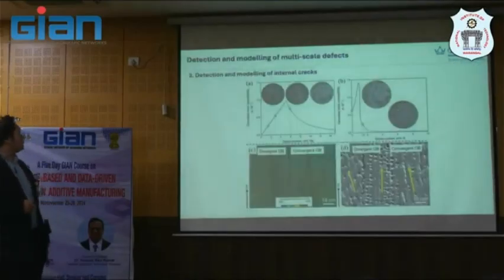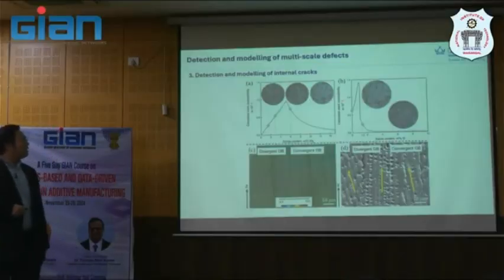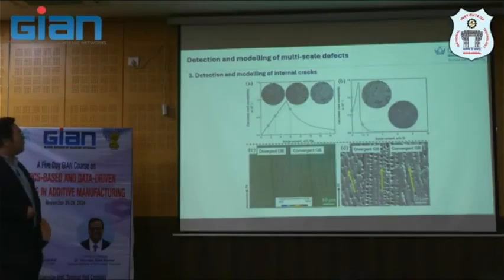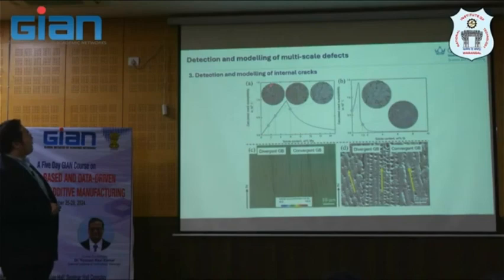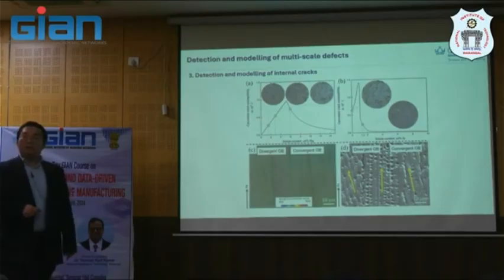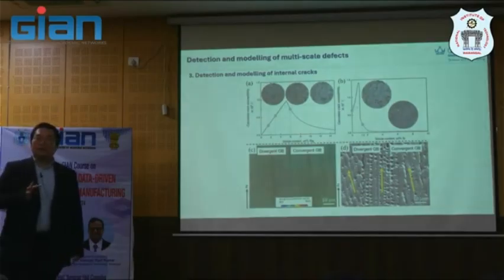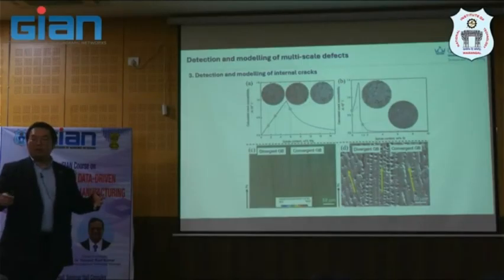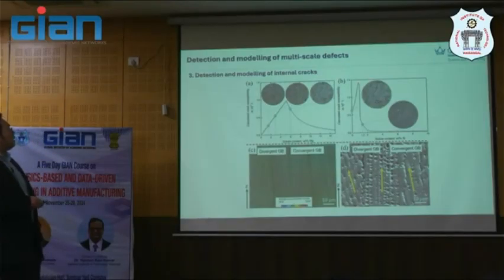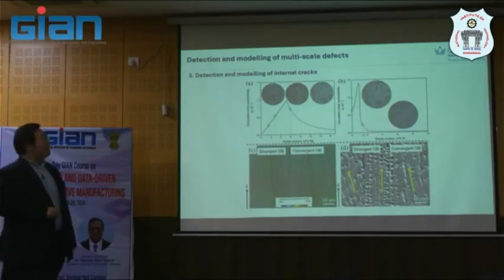printing. Next one is about internal cracks, and again this is related more to the solidification features that you will see. The cracking depends on, you see this calculated crack susceptibility. This is a calculation. It depends on the solute content. That means it depends on the elemental profile within your metallic sample, because we are talking about metal things, right? Solute content here at the different conditions will vary as well, and these lead to different